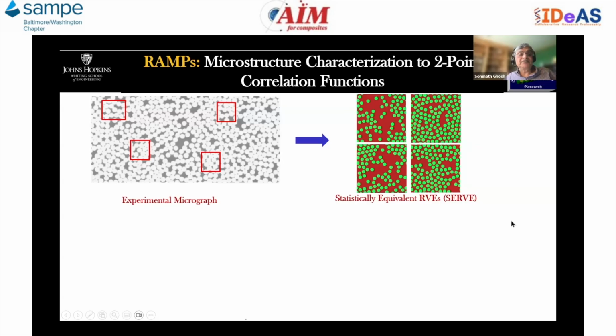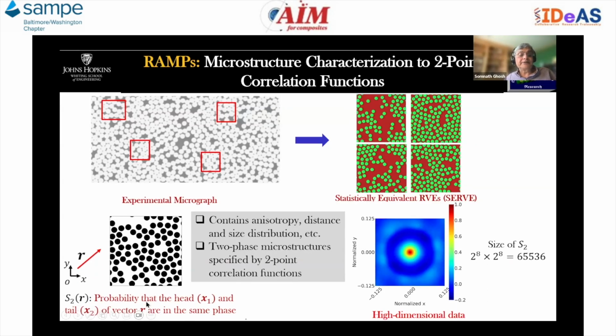So the first step corresponds to the microstructure. This is an experimental micrograph that we are characterizing using the 2-point correlation function, S2, which produces this high dimensional data. This S2 is the probability that if you put a position vector R here, the head and the tail of the vector R are in the same phase. That is literally the meaning. It contains anisotropy, distance, and size distributions, and a two-phase microstructure specified by 2-point correlation functions. It's a fairly good representation of these two-phase microstructures.